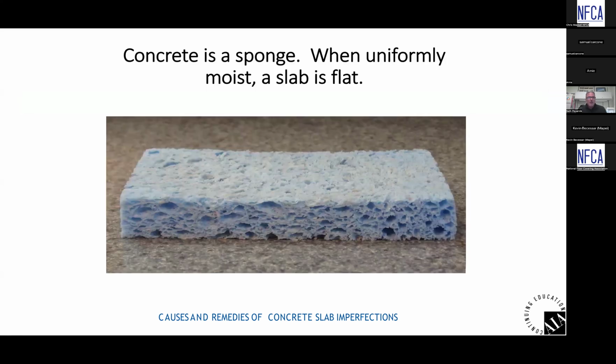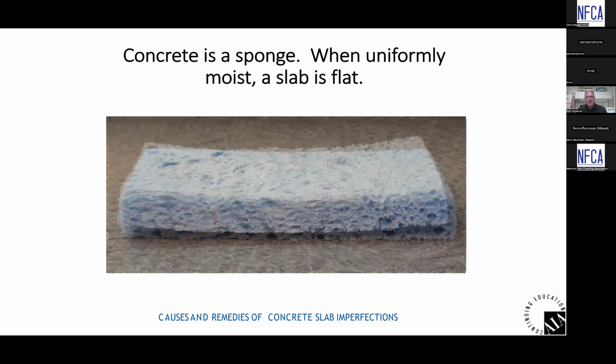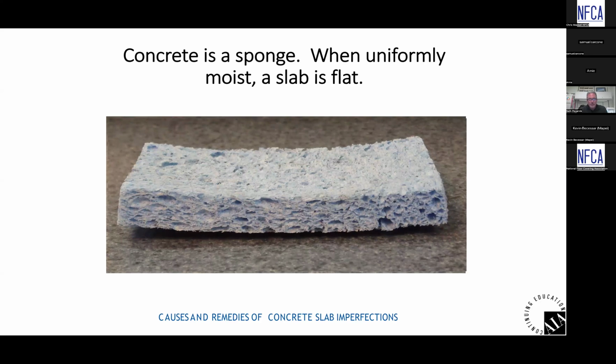in that concrete. So to put this into perspective for you, I've got some time-lapse photography going on here. This is a damp sponge, a totally saturated sponge, not dripping with water, but damp, totally 100% saturated, and it's sitting on a piece of plastic laminate countertop. That countertop is acting like a vapor retarder underneath the concrete. So similarly, when this sponge is totally saturated and the water in the sponge can't absorb down because of the plastic laminate countertop, when this sponge dries out, it curls, as you see in the time-lapse photography. You've got the edges that are curled up.